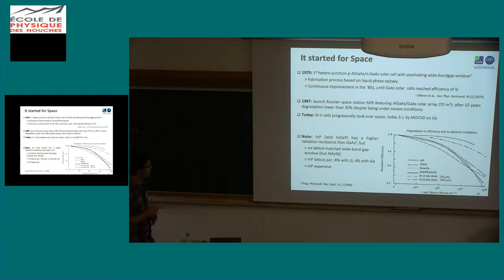At that moment, the fabrication process was based on liquid epitaxy. I'll come back a little bit to the different techniques of epitaxial growth we use today. And the improvement started to get better efficiency for III-V solar cells compared to silicon. And till nowadays, we normally use triple-junction solar cells, normally made by MOCVD, again I will come back to these technologies, grown on germanium, because germanium is cheaper than gallium arsenide and more mechanically robust.